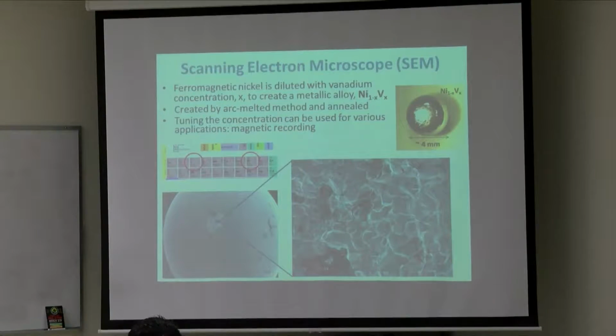So if we take a look at what the SEM does, it actually takes really nice pictures. This is a material that I created as a graduate student. This is nickel vanadium, so ferromagnetic nickel, and you dilute it with vanadium. The idea was to do magnetic measurements because I was interested in knowing the magnetism of the material. But nonetheless, this is the sample that I created. I used an arc melt method, so basically I cut up specific concentrations of the material, melted them together, and created this really nice shiny sample here.